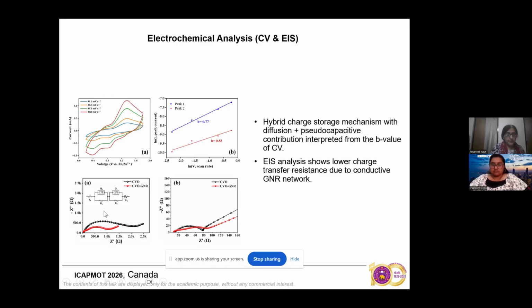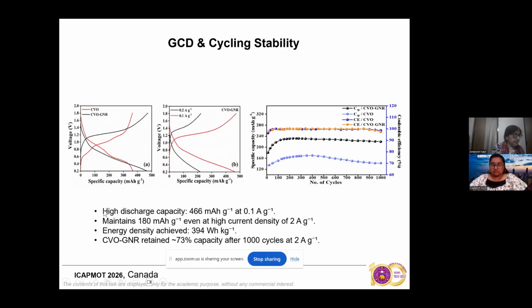So now, we did the galvanostatic charge-discharge also, and we calculated the discharge capacity. The discharge capacity of the device is 466 milliampere-hour per gram at 0.1 ampere per gram. It's a very good value, and the only thing is that it has to maintain its value as much as it can, but the discharge capacity is 180 milliampere-hour per gram even at the high current density of 2 ampere per gram.